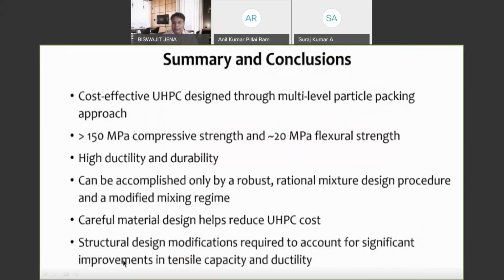So, in summary, you have a multi-level particle packing approach, both for the paste fraction and for the aggregate fraction. The paste fraction is by packing of particles and rheology, and the aggregate fraction is by what we call a compressible packing model. But you can use any kind of packing model. You can have very high compressive strength, flexural strength, ductility is also very high, durability is also very high, and we have done cracking tests. Cracking propensity is low, provided you cure them really well.